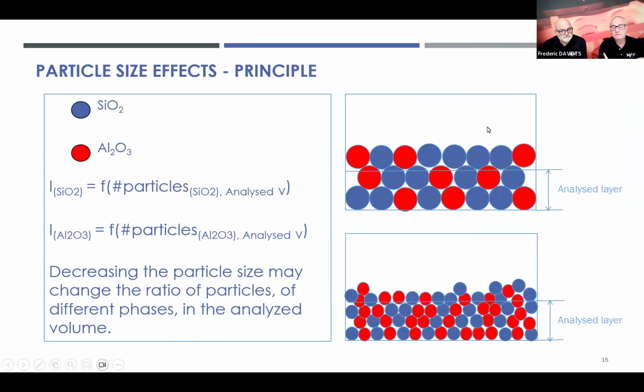So the first parameter is particle size effects. Here I'm just showing a simple example where we have silicon oxide and aluminum oxide grains. In the first case, the upper graph, we can see quite large grain size, and our X-rays will penetrate into our sample, and X-rays will come out of our sample. And the analyzed layer really shows the depth from which we get information from our sample.